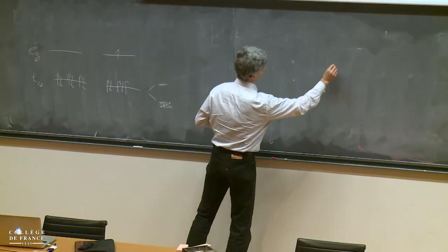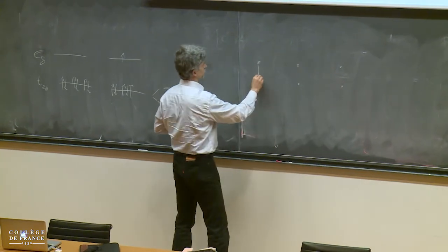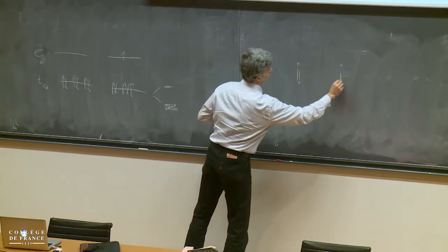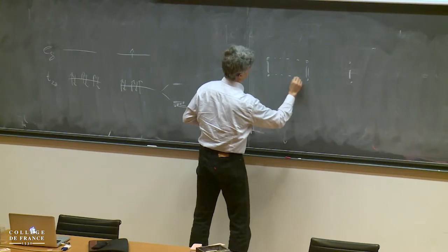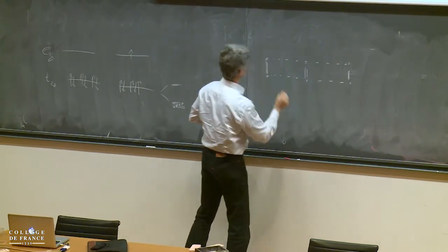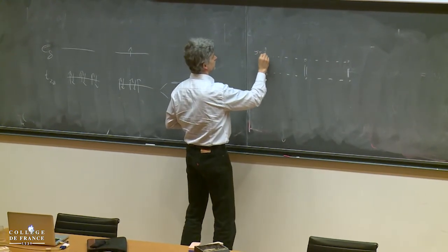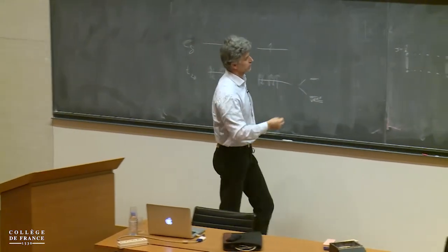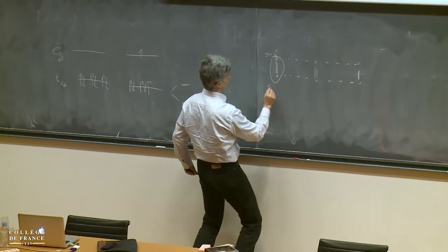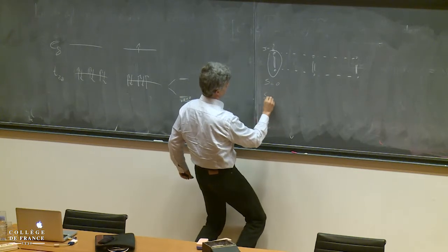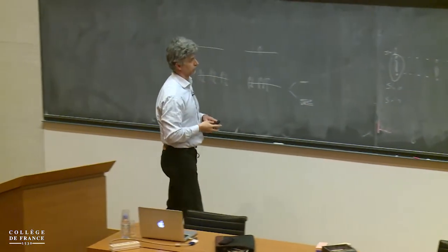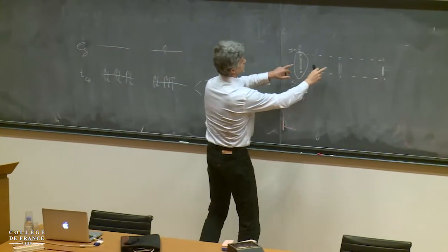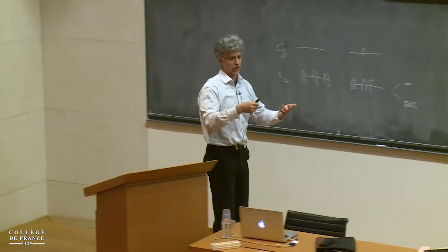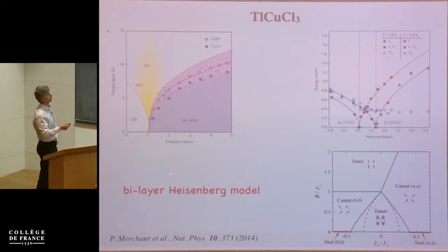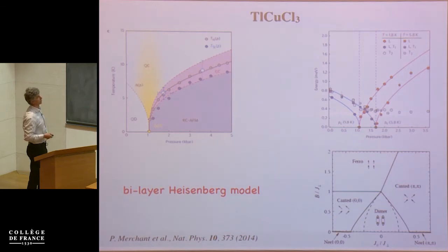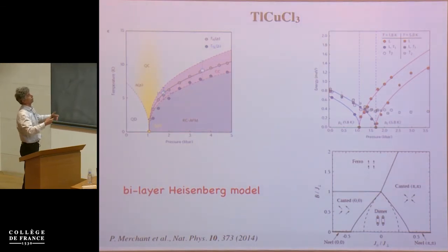So you can imagine a material where you have antiferromagnetically coupled dimers, which are coupled by some weaker coupling, and you have spin 1/2 on each side. Then in this dimer basis, you can have a total singlet or total triplet, and depending on whether the coupling between these dimers is strong or weak, you will have either a trivial singlet global ground state, or some non-trivial long-range order.